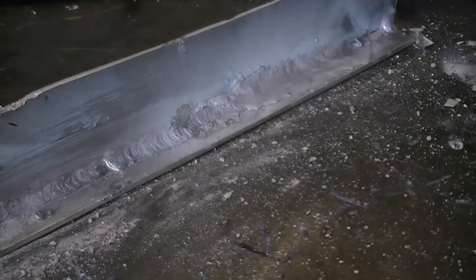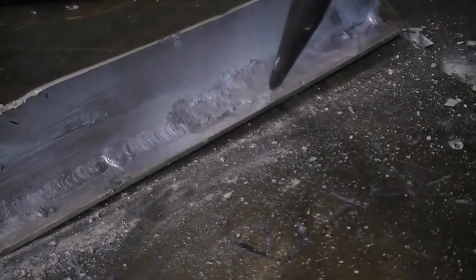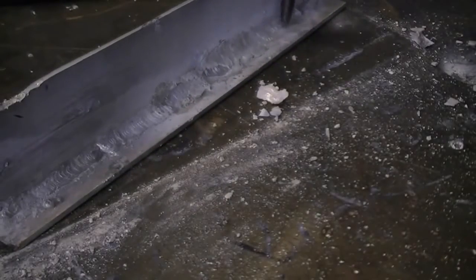At this point, we made some changes. We reduced the amperage by 15 amps to 105 amps and increased the hot start for a smoother start. Then we increased the arc force up to 50%. At this point, the slag became difficult to remove and required a more intensive effort.